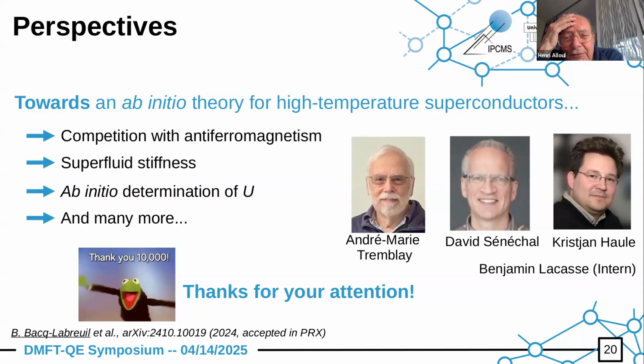Okay. Yes. Very interesting work indeed, because we have been waiting for this kind of work for long, because the NMR has shown at the beginning that difference between the inner plane and the outer planes. I have one question which I think you didn't address: what do you find about the pseudo gap in the inner layers? NMR experiments have shown that there you are really in the underdoped regime, and see a pseudo gap while the outer layers do not, in some of the compounds. I don't know, I think in Bi-based compounds. So do you have any indications going that way? Because you are saying that you change the charge transfer or something like the charge transfer gap.